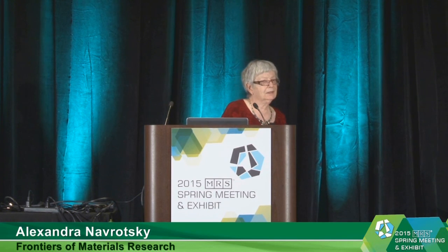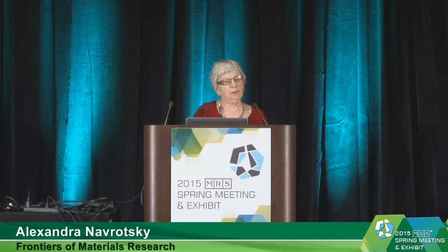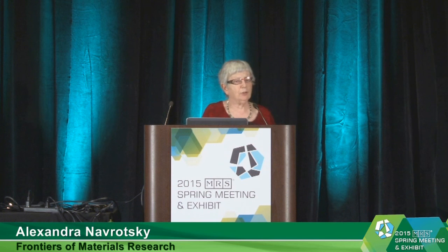Thank you, Professor Navrotsky. I'm quite new to this area, so I just want to ask, how do you define the surface energy? Is it just using the contact angle to melt the certain material? No. In this particular case, and I purposely did not go into the methodology, we measure it calorimetrically. The ideal measurement is you make materials of different surface energies and you dissolve them to the same final state. You can think of it as dissolving it in water. These are ceramics, so we dissolve them in a high temperature oxide melt, and then we get the energy as a function of surface area.